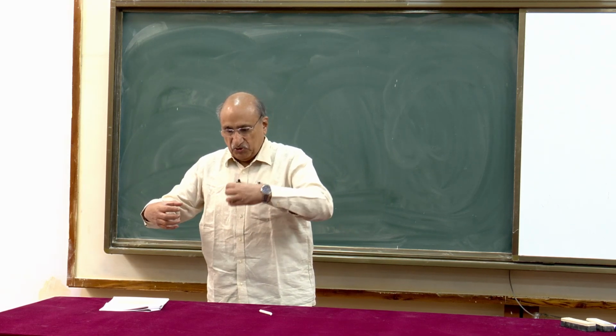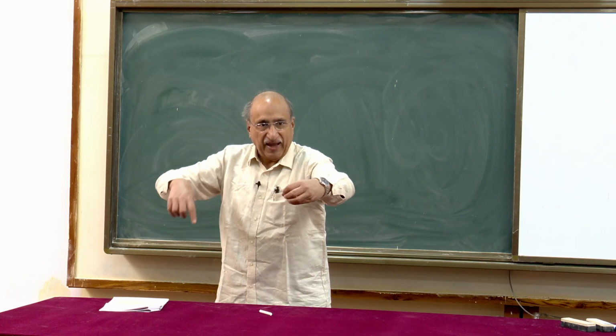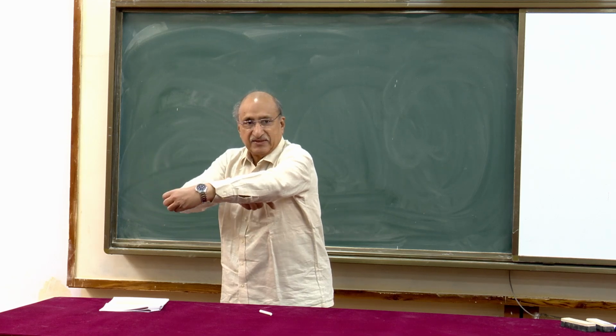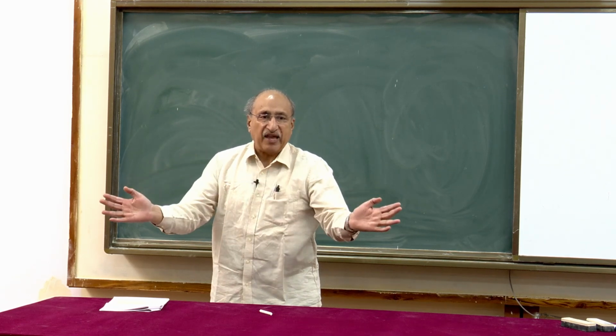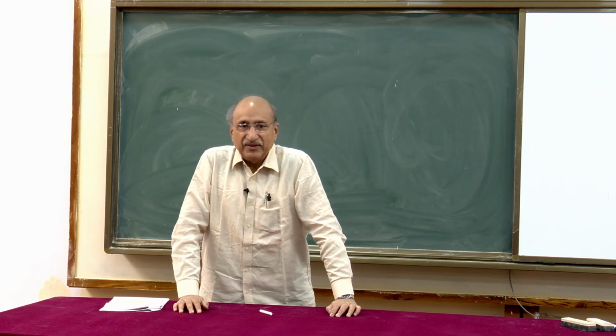But suppose this bond is like this, and another bond is like this. So it depends on the angle. The smaller the angle, for example if you have one like this, then the exchange interaction will be very low. So basically, the larger the angle between the two bonds, up to 180 degrees, the interaction will be maximum.